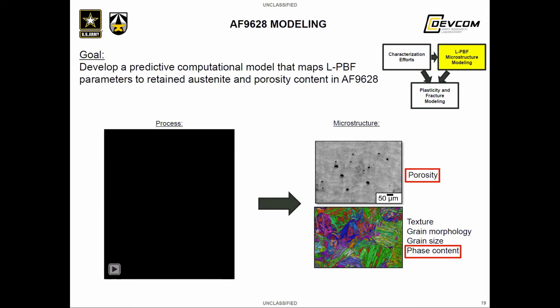As I listed before, the two main microstructural features of interest highlighted here are porosity and phase content, specifically the amount of retained austenite within the steel structure. Microstructural simulations depend on the knowledge of the thermal history of each region of the part as a function of time. The thermal history is used in conjunction with various types of thermodynamic modeling of phase transformation at different length scales. This modeling can take various forms, from empirically defined functions to phase field modeling to CALPHAD and other types of modeling. The key input to any microstructural model, however, is a detailed and accurate representation of the part's thermal history throughout its entire volume.